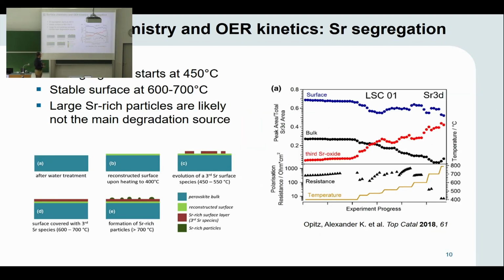And we can monitor then, as a function of temperature, how these species evolve with temperature and time, and also monitor the electrochemical polarization resistance at the same time. And what we can see here from this experiment is that the bulk strontium component decreases, which means it gets overgrown primarily by the strontium oxide species. And this process already starts at 450 degrees, which is relatively low, given that in bulk diffusion experiments, you would expect that cations stay on their lattice site at this temperature.